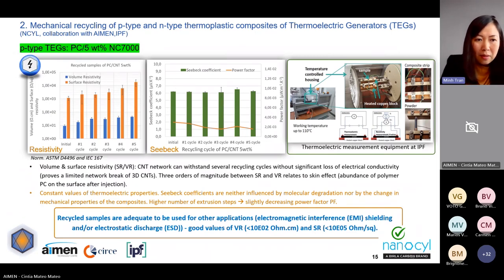However, concerning the resistivity, we witnessed a significant increase of the surface resistivity. The volume resistivity, however, we maintained within just one order of magnitude. And the thermoelectric properties generally remain the same. The conclusion is that for the reuse and recycling of the P-type TEG based on polycarbonate and multi-wall carbon nanotube, we target the mechanical properties rather than the electrical conductivity. Next slide, please.